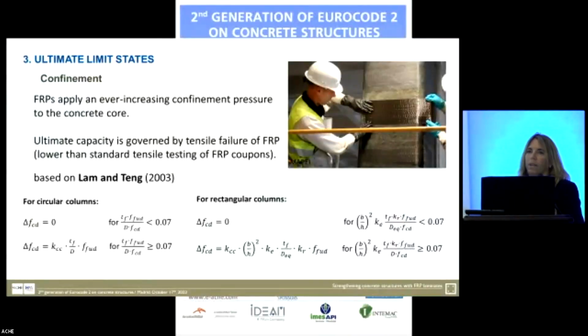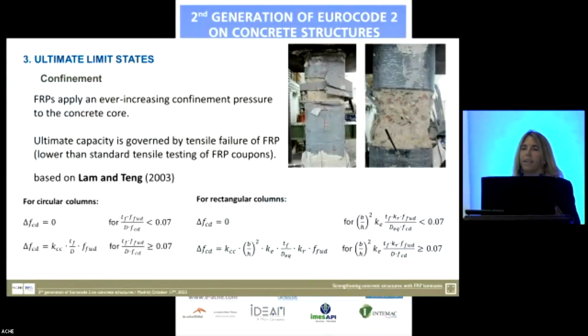If we move to confinement, it's well known that by confining a column or an element that is subjected to axial forces, we can increase its bearing capacity. And the FRP might be used for confining the columns. The only point is that the ultimate capacity of this structure confined by FRP is governed by the tensile failure of the FRP. The tensile strength is slightly lower than the tensile strength that we have when we do a tensile test with this type of material, because of the multi-axial stress state of the column, and also because we have some stress concentration in the round corner of the columns.